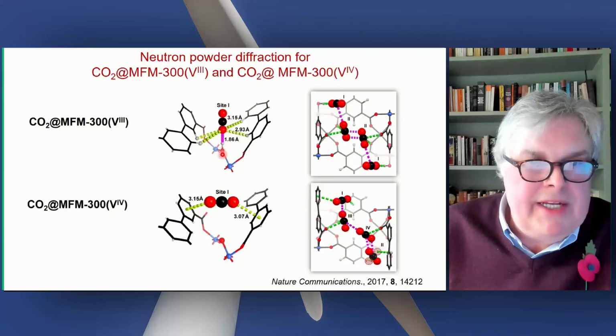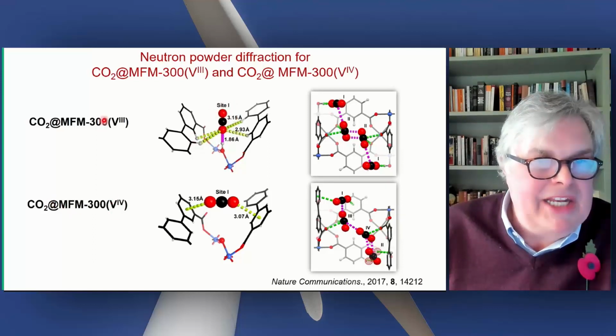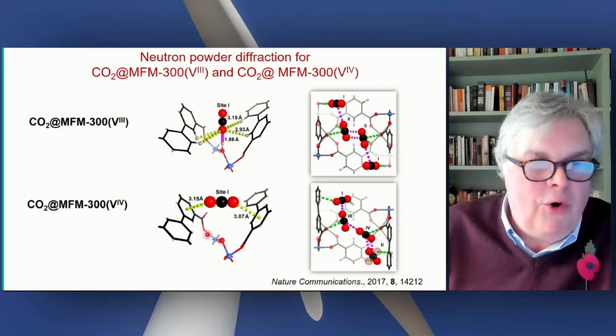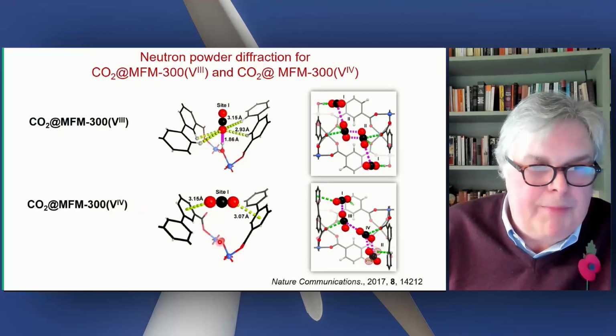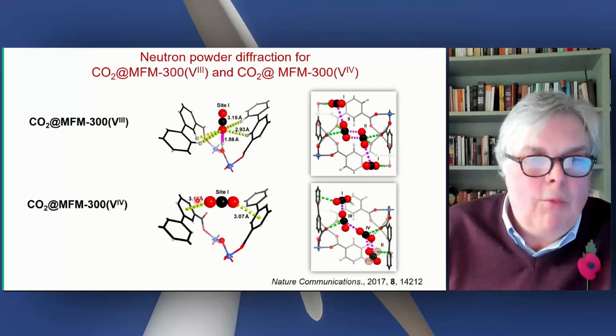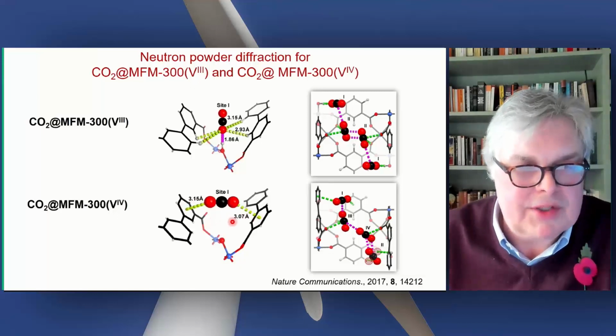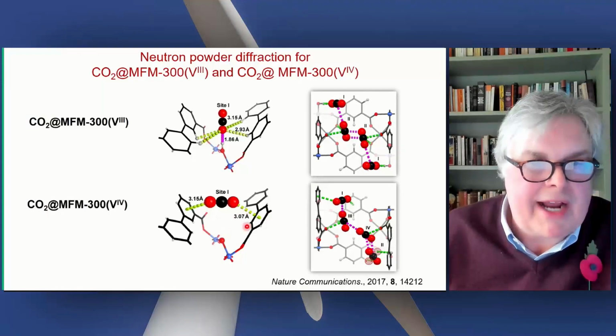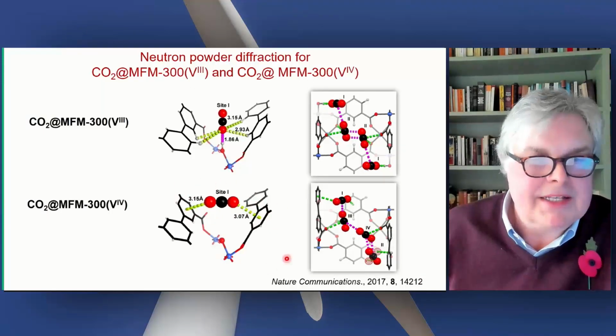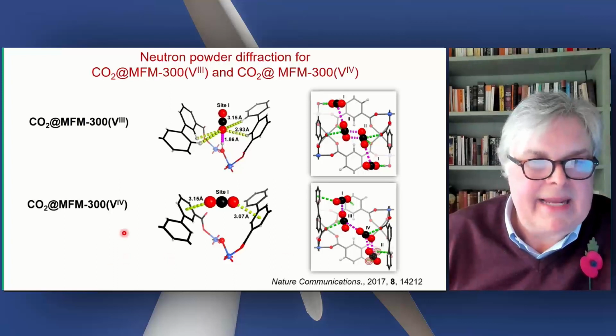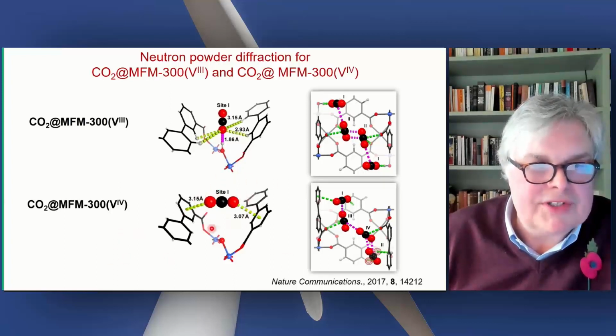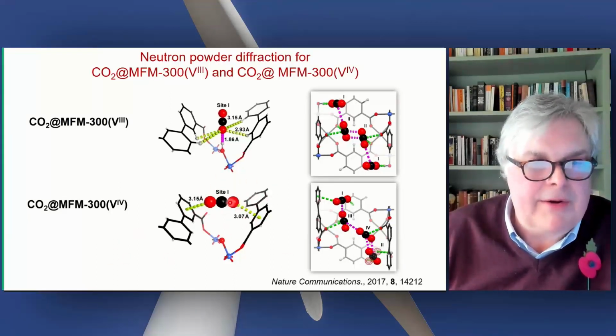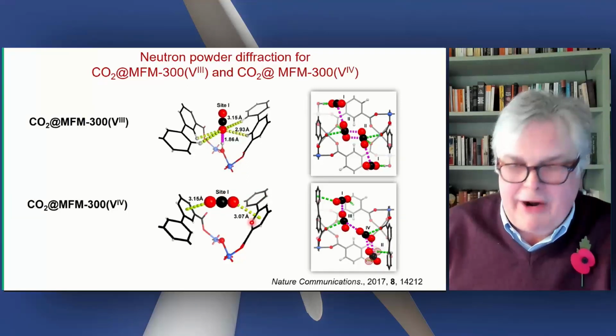Here is the CO2 interacting with the vanadium hydroxy, the 4 CH interactions onto the CO2. You now go from vanadium 3 to vanadium 4. You have lost the OH group here. Here is the oxo group. What happens is that the CO2 twists, and it now interacts with the aromatic groups, which is quite exceptional. It's a weak interaction, and I would certainly not describe this as a CO2 capture agent, but at the same time, it does show very interesting fundamental chemistry here about CO2 interacting with polyaromatic groups.